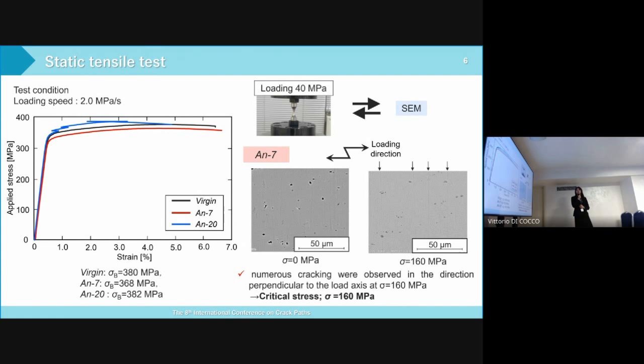This is the static tensile test result. The test condition is shown here, and the vertical and horizontal axes are applied stress and strain, respectively. As a result, virgin, AN7 and AN20 have tensile strengths of 380 megapascal, 368 megapascal, and 382 megapascal. So anodizing treatment hardly affects tensile strength.